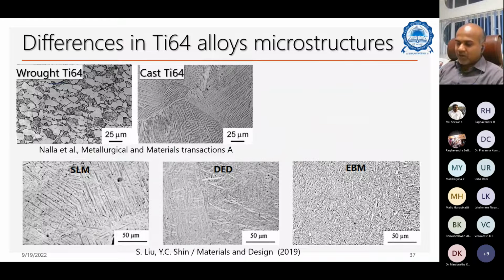If you look at the Ti6Al4V alloy, wrought Ti6Al4V and cast Ti6Al4V, cast will have certain features like this. These are called prior beta boundaries. And these are certain lath structures that you see in a cast structure in cast Ti6Al4V. After casting, you process that using processing maps, as I told you before. What you get is a very uniform grain size structure with alpha phase and alpha plus beta phase. That's what you get here.